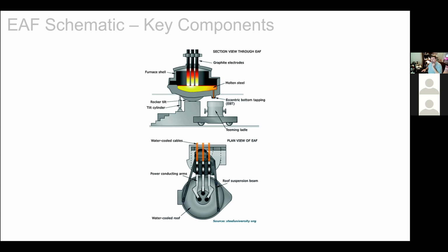So what we do is we pass a current from one graphite electrode through the scrap back to another graphite electrode. And as that current passes through, the scrap has resistance to the flow of the current, and we end up with joule heating, I squared R. So that's the whole concept in a nutshell behind the electric arc furnace.